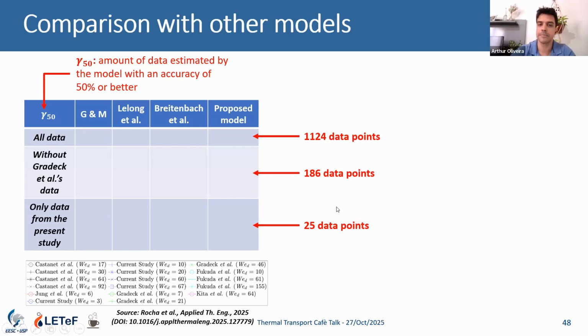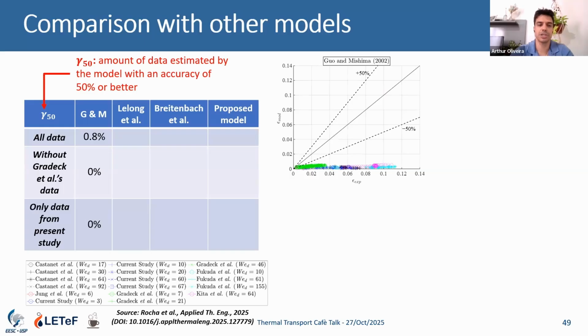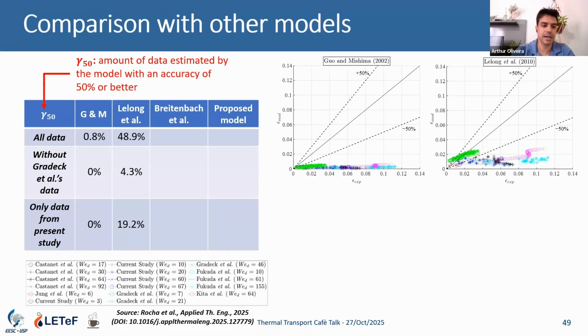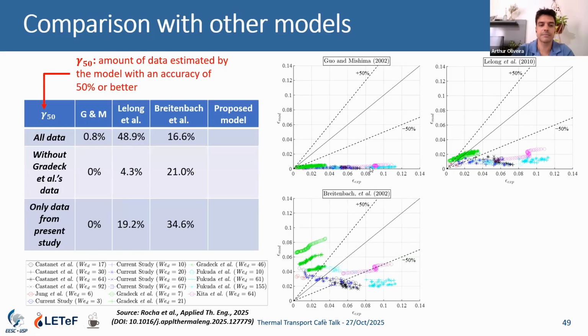When you see this, Guo and Mishima's model performs quite poorly compared to the data. It underestimates a lot the cooling efficiency. Lelong's data performs very well using Gradeck's data, but with the others it underestimates the results a little. When you take Breitenbach and colleagues' model, it captures well the order of magnitude of the cooling efficiency, but there's something missing in the trend. It goes much better than the others for a moment.